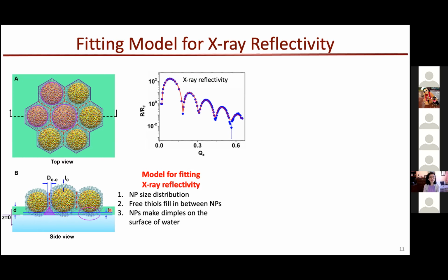Third, we allow the nanoparticles to form a dimple at the interface, as inspired by the MD simulation, and we introduce a height parameter, the bottom of the core to the surface of the water. Then we use a hexagon shape for the liquid shells instead of a spherical shape, and finally we model the free thiol film as a liquid film with variable thickness D.